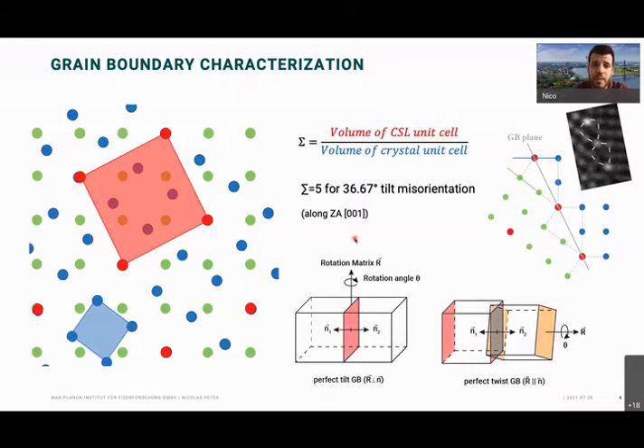There are other things that characterize a grain boundary: the grain boundary normal and the rotation angle. If they are aligned perpendicular to each other, then we call it a tilt grain boundary. If they are parallel to each other, then we call it a twist grain boundary. But for today, we will only talk about tilt grain boundaries in this sigma 5 system, because that makes it easy. If we look along this orientation here, then we see it's always the same. We only rotate the letters around this axis. So we have two axes in the two grains being the same, which is important for the electron microscopy study that we want to do.